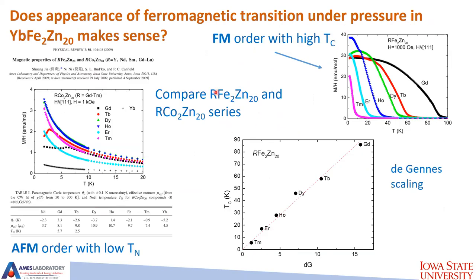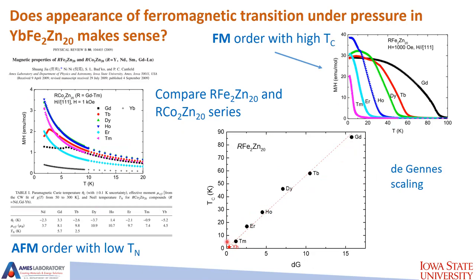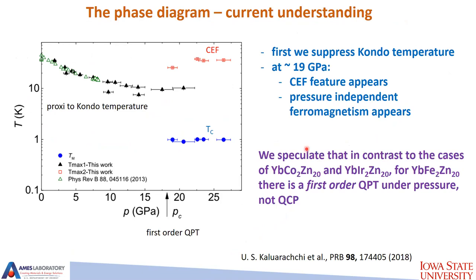Similarly, if you compare different rare earth iron zinc 20 series with different rare earth cobalt zinc 20 series, for all cobalts it's antiferromagnetic transitions with very low ordering temperature. For all irons, it's ferromagnetic transitions with significantly enhanced temperature in comparison with cobalt. Moreover, there is the de Gennes scaling for ferromagnetic ordering temperature, and if you put our data for ytterbium, at least it doesn't violate it. It lives where it's supposed to live, at one Kelvin or so. So basically, we speculate that that's what is happening.